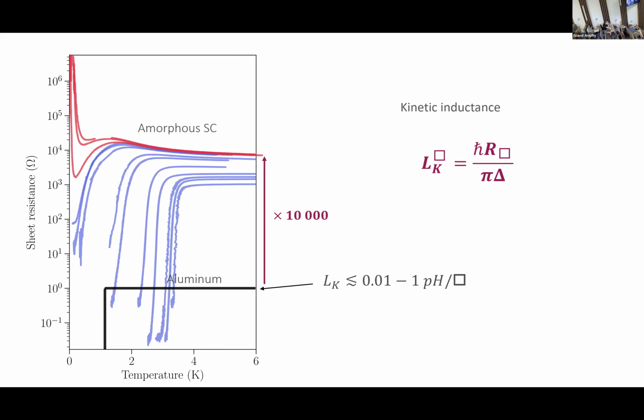This is the superconductor-insulator transition. You have a variety of transitions and possible intermediate states. But you have materials where this resistance can shoot up very high. We have seen it in indium oxide. We have seen it also in niobium nitride with Christoph Strunk. It can reach nearly 17 kilohm per square. And this gives you, naturally, if you believe this semi-classical Mattis-Bardeen formula, a boost of kinetic inductance by the same order of magnitude. Now you can get values of the order of 0.1 to maximally 10, actually a little bit more, 17 picohenry per square. So the point of application is to take benefit of this inductance in possible circuits and applications.